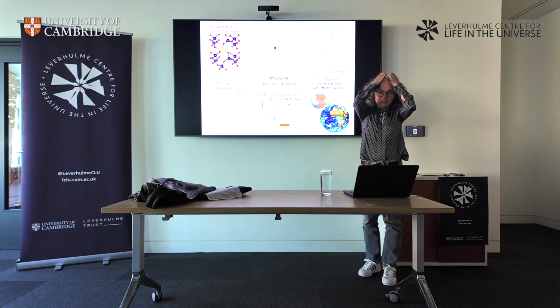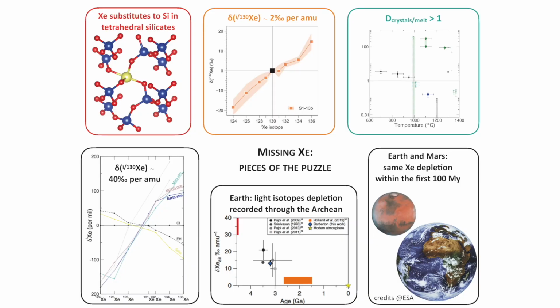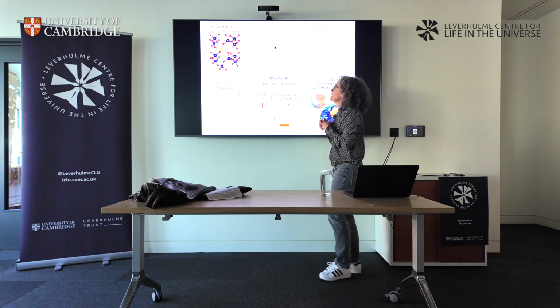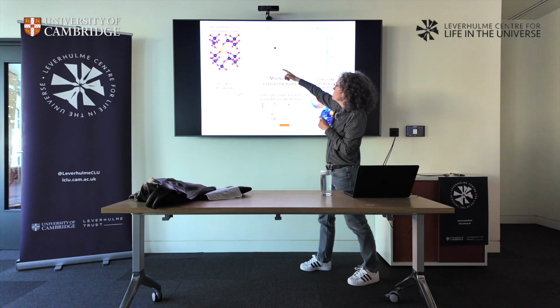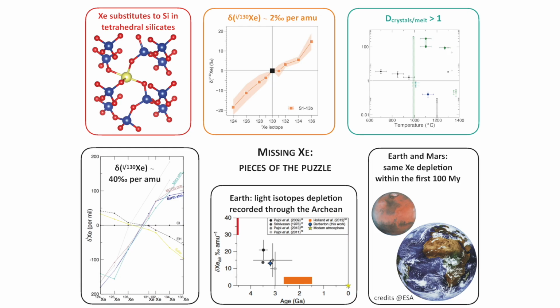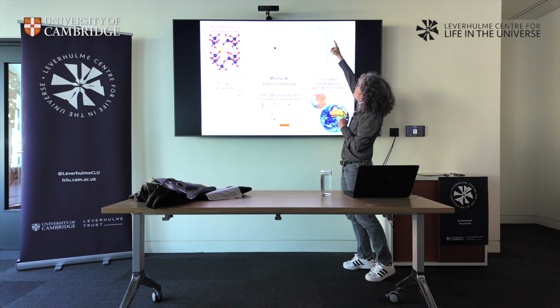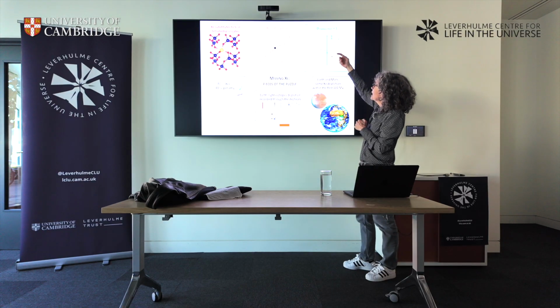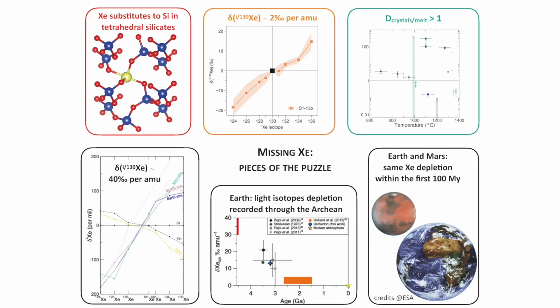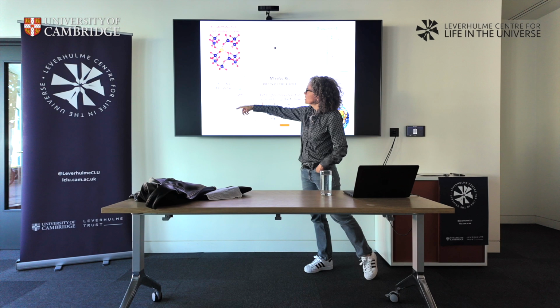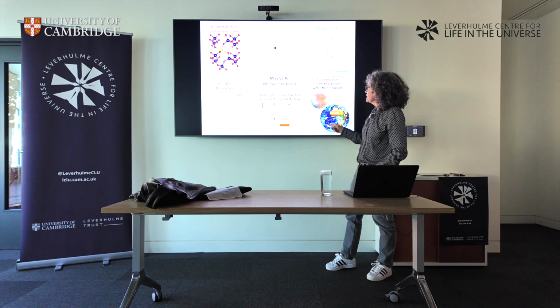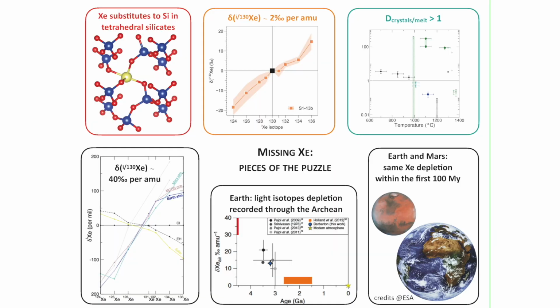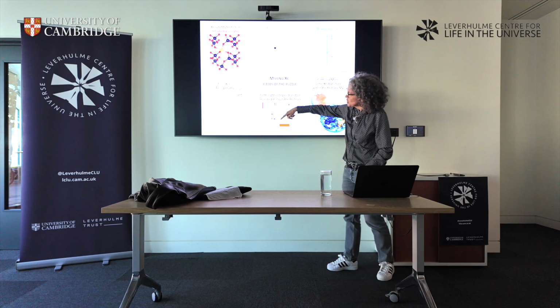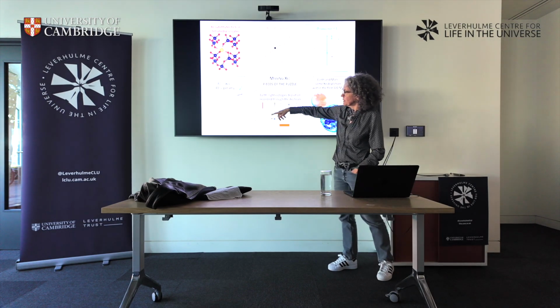So let's try to put all the puzzle pieces together. In the crystalline silicates, we have xenon substitution to silicon atoms bonding to oxygen. That's what ab initio calculations tell us. We observe mass-dependent fractionation of xenon on our recovered sample. Not for all crystal-melt systems, but for some of them, and in particular for olivine, we have trapping of xenon in the crystal at equilibrium with the melt. So that's experimental, and now the observation: strong depletion in light isotopes, and the same xenon depletion for the Earth and Mars. Last thing, this strong depletion in light isotopes is recorded differently throughout the Earth history.